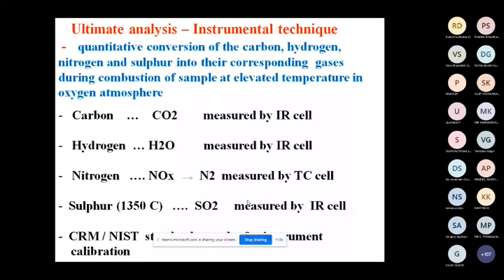Nowadays, instrumental techniques have come. Instrumental technique for carbon, hydrogen, nitrogen, sulfur: the quantitative conversion of carbon, hydrogen, nitrogen, sulfur into their respective gases during combustion of the sample at elevated temperature in oxygen. As I said earlier, carbon will be converted to carbon dioxide measured by IR cell. Similarly, hydrogen will be converted to water measured by IR cell, infrared cell. Nitrogen will be converted to NOx. Again, through a catalyst, it will be converted to nitrogen that is measured by thermal conductivity. Then sulfur, at very high temperature, 1350, is converted to SO2 measured by IR.